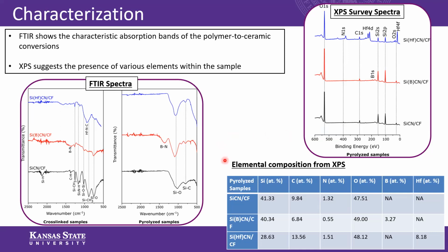And in this chart, the elemental composition from XPS is shown. So the values shown are quite expected for each type of sample. Silicon, carbon, nitrogen, and oxygen were present in the expected amount for each type of sample: SiCN CMC, SiBCN CMC, and SiHFCN CMC. And then, of course, for the SiBCN sample, a significant amount of boron was present. And for the SiHFCN sample, a significant amount of hafnium was present.